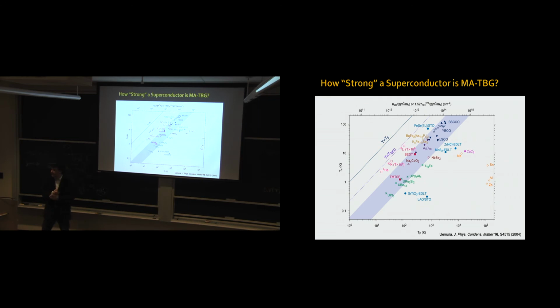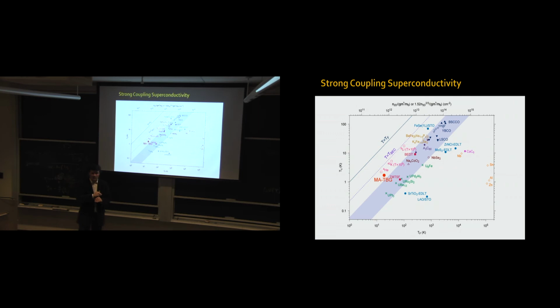So where is magic angle graphene in this plot? It happens to be right there. It's one of the strongest coupled superconductors that we have. In fact, in 2 dimensions, it is the lowest density superconductor by well over an order of magnitude with respect to the next lowest density superconductor. In fact, if you measure the superconducting coherence length, the size of our Cooper pairs in magic angle graphene is just a little bit bigger than the interparticle spacing in terms of density of electrons. Super low density. Our Cooper pairs are just barely bigger than the interparticle spacing.